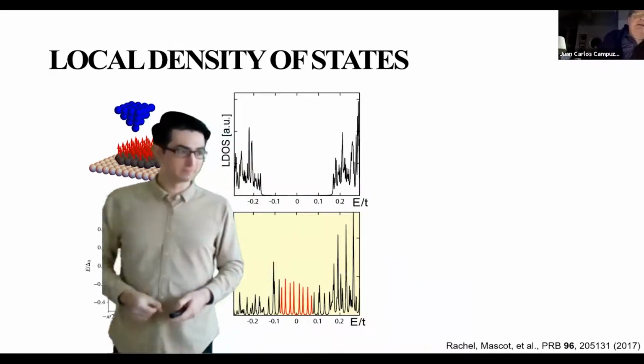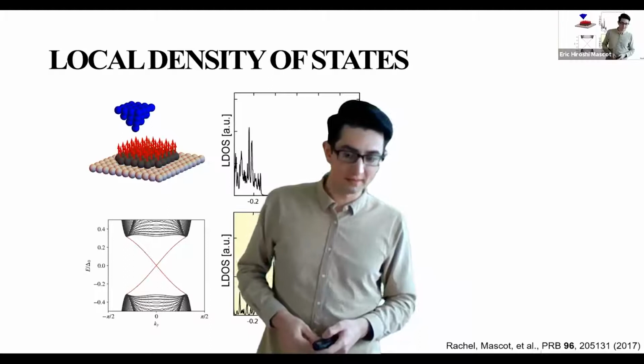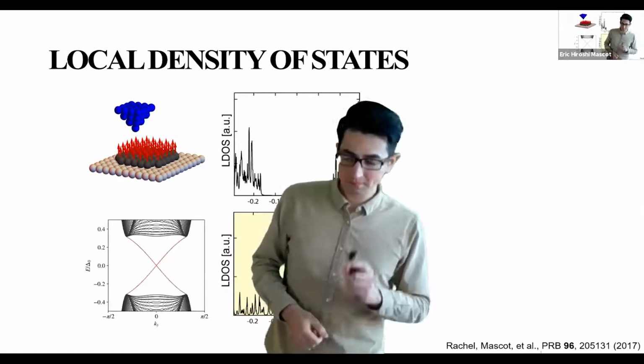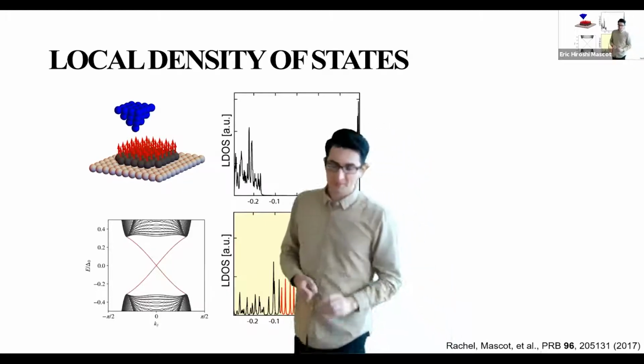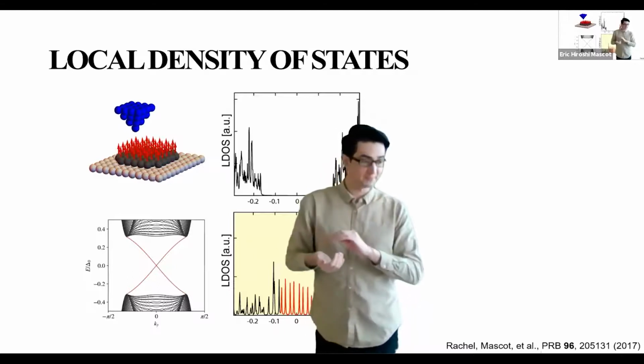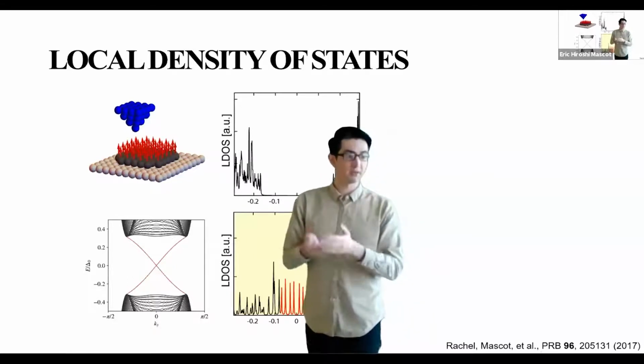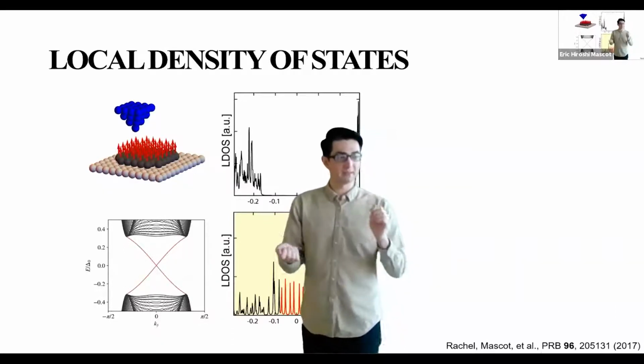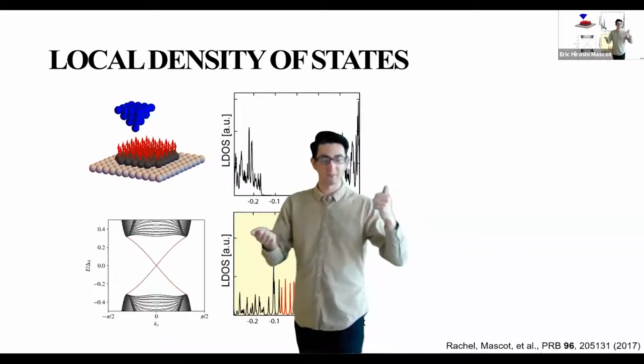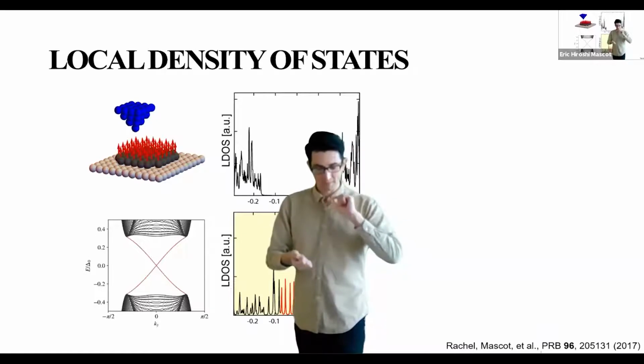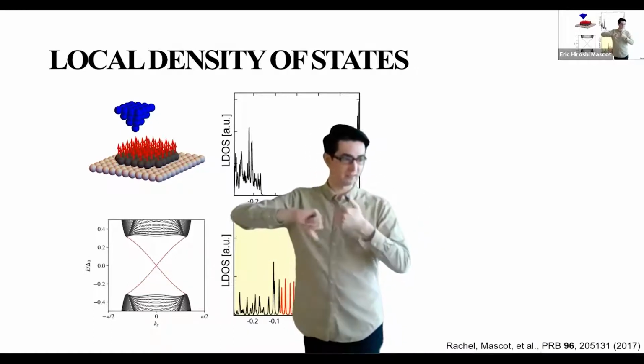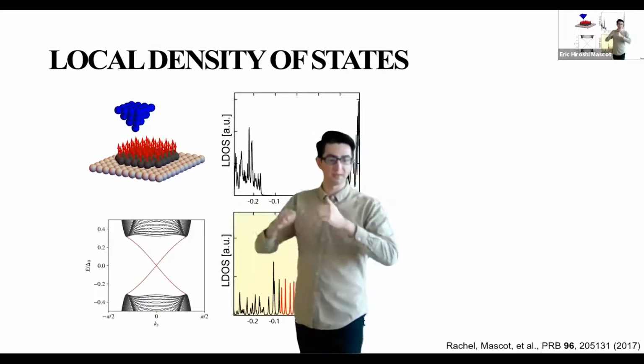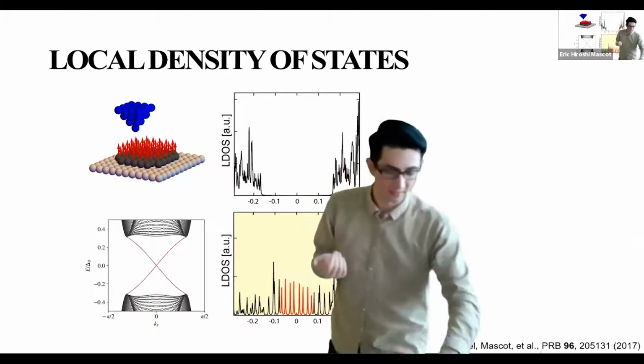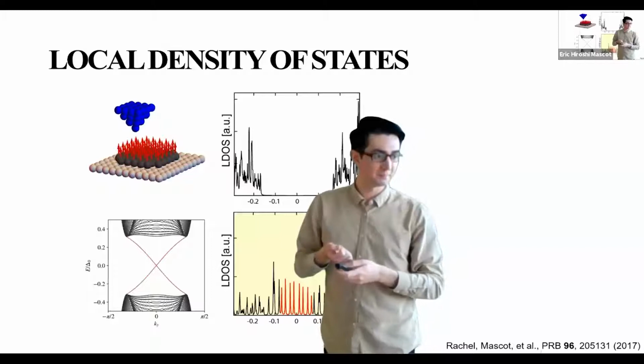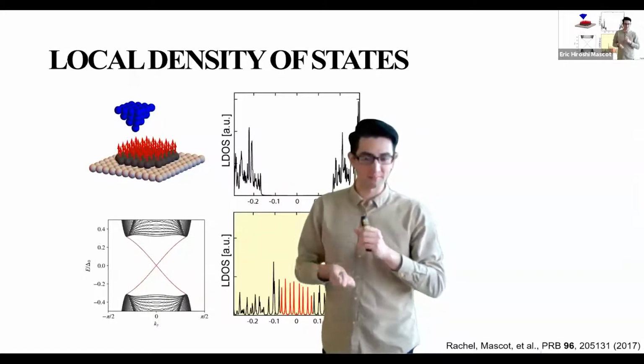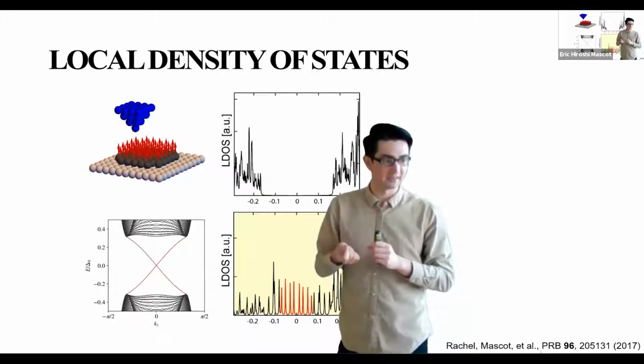Sorry, how do you make sure that the magnetic island doesn't destroy superconductivity? Yes, so if we were to not have spin orbit coupling, the magnetic exchange in this system is strong enough to destroy that superconductivity. But by having a Rashba spin orbit interaction, we're gapping... usually we have a singlet pairing, but with the spin orbit interaction, we're able to have a P-wave-like gap. And so it's because we have spin orbit interaction that we have a gap even though we have magnetism.